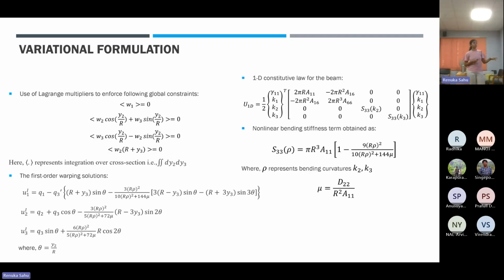Using these warping solutions, we can get the 1D constitutive law for the beam, wherein you have your 1D strains gamma 1, kappa 1, kappa 2, kappa 3 which are the curvatures. The A11, A16 terms are the normal stiffness terms which we get from the classical laminate theory.